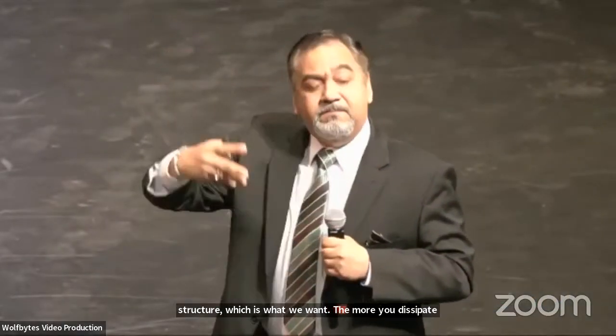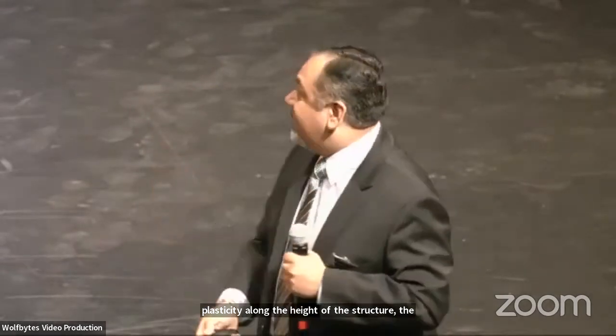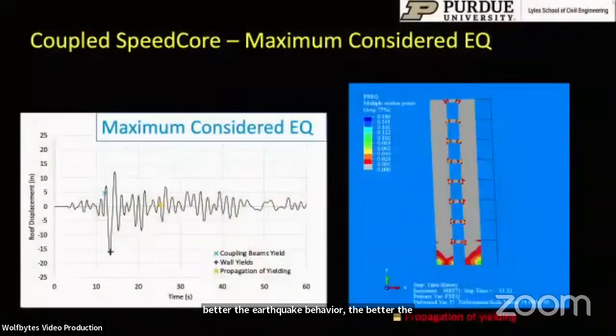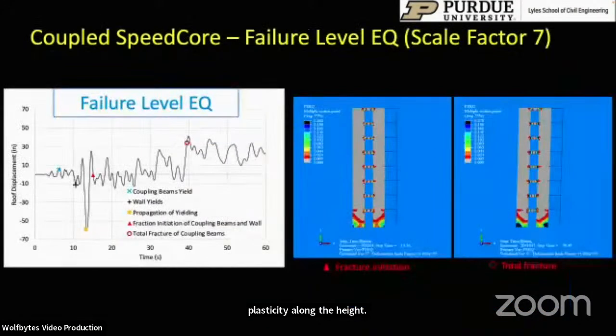The more you dissipate plasticity along the height of the structure, the better the earthquake behavior, the better the ductility, and the larger the R factor. So we were able to achieve that by spreading the plasticity along the height. You do still get some formation of plasticity at the base of the walls. But when you consider the failure level earthquake, all those events that we had identified occurred in the right sequence.